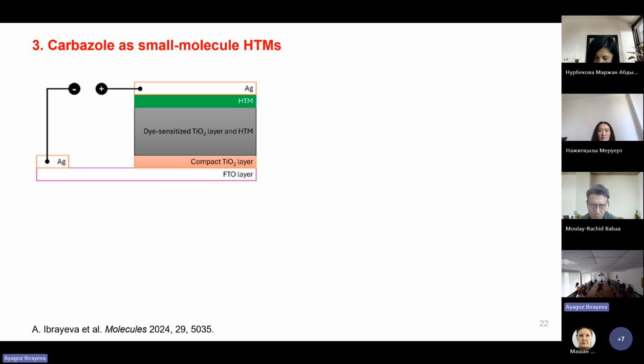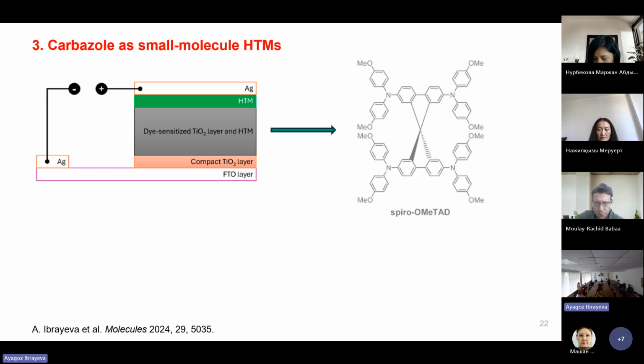For the third direction, after completing the quasi-solid electrolytes, we shift to solid-state electrolytes. Here, the solar cells are fabricated differently. Instead of liquid electrolyte, we have hole transporting materials, and as a counter electrode we used silver. Today, the most popular hole transport material is spiro-OMeTAD, which has good photovoltaic performance. But the problem is that it has a complicated synthesis and is expensive.